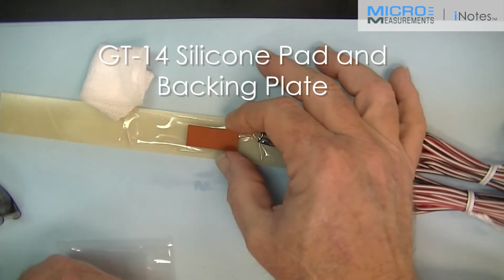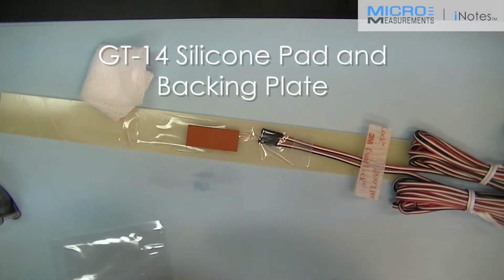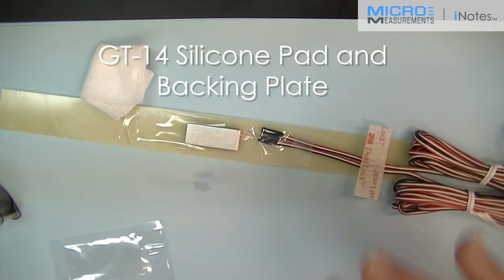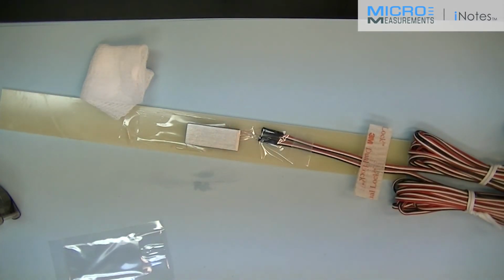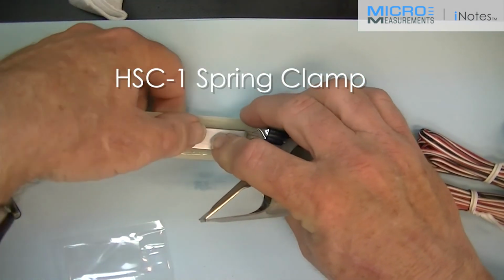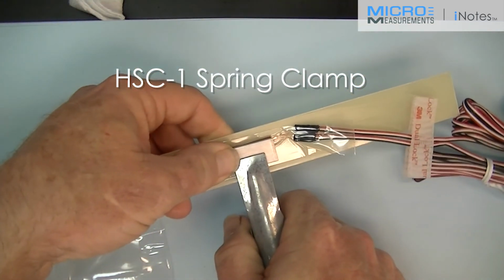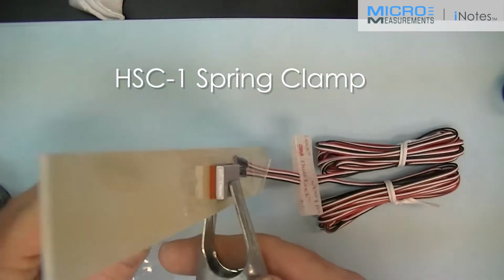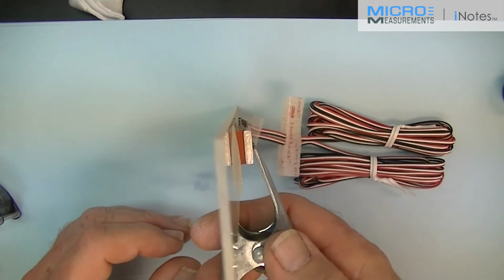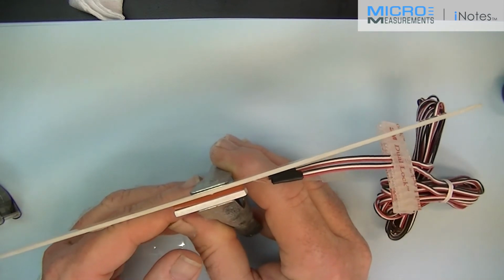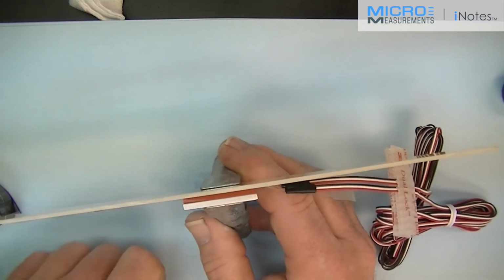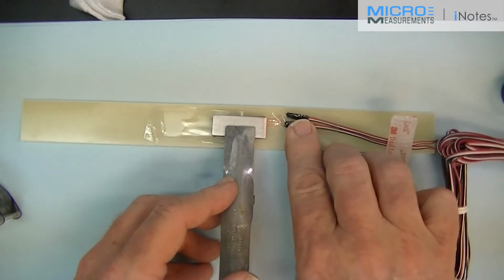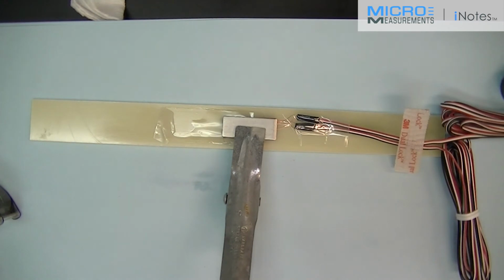Locating a silicone gum pad, I'm going to place that directly over the gauge, an aluminum backing plate, and finally a HSC-1 spring clamp for applying the clamping pressure to our adhesive system. I'm now going to check to make sure that the aluminum backing plate and the fiberglass beam are parallel to one another, both in this direction and this direction, ensuring that I have even clamping pressure. I now leave it for a minimum of 6 hours if I'm going to cure it at room temperature, or I can elevate the temperature and cure it quicker through an oven process.